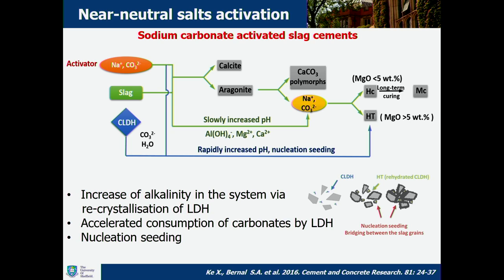But when we include this smart addition, the calcined layered double hydroxide, we see three effects. One is an increase in the alkalinity of the system, because the layered double hydroxide will recrystallize, so it will absorb some of the water within the system. Also, it will accelerate the consumption of carbonates. And finally, some of the particles of this layered double hydroxide actually work as nucleation points. So everything sounds really nice, to be honest, from a chemical perspective.